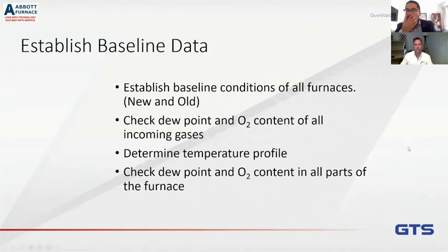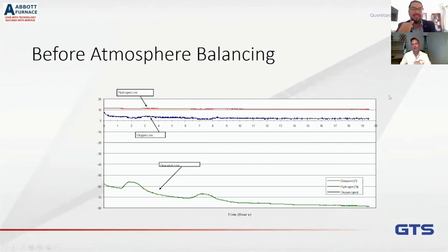So when we discuss furnace brazing, you always bring a really nice example of the before and after. Can you show us that? Yeah, please. Thank you. When you introduce atmosphere into your furnace, you put it in the cooling section. And remember, we said we want that hydrogen to go forward because it's expensive. We want it to do the work in the hot box. We only want about 10 to 20% of that to go back towards the back of the furnace, and we want that to mostly be nitrogen, because all it's doing is keeping air out and allowing the product to cool.